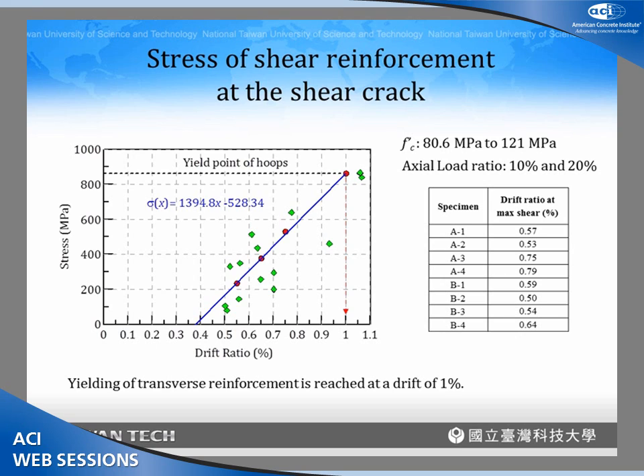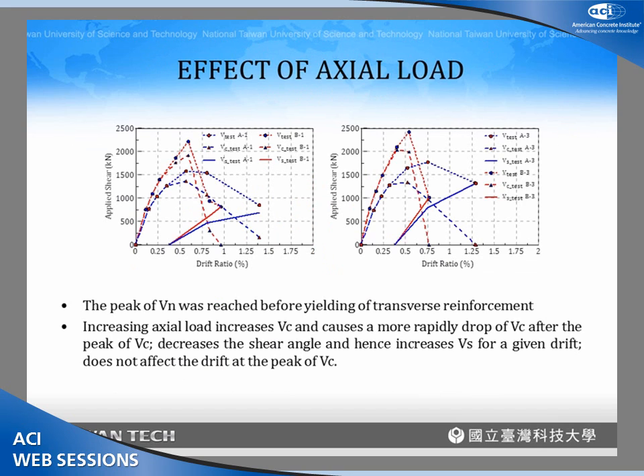And this table shows you the drift of each column at the peak applied shear. So they are all smaller than 1% drift ratio. This means that at the peak applied shear, the transverse reinforcement is not yielding.